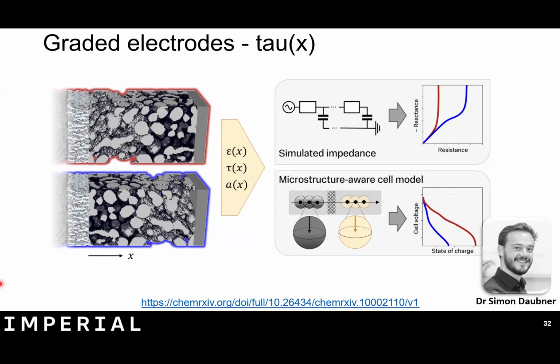Once you've generated your 3D microstructure, of course, then you want to extract performance relevant metrics. So if you're a battery, this can be volume fractions, surface areas, effective transport metrics. However, some structures are intrinsically graded, and really basically all battery electrodes are graded to some extent in the sense that their microstructure varies as a function of depth through the electrode. So the microstructure will be a little bit different next to the current collector as it will be next to the separator. And this can be inadvertent because you dry it too quickly and the solvents have come off too fast, leaving the binder non-uniformly distributed, or it can be deliberate and you can improve the performance of your electrode because you need more electronic conductivity close to the current collector and more pore space for ionic conductivity next to the separator.